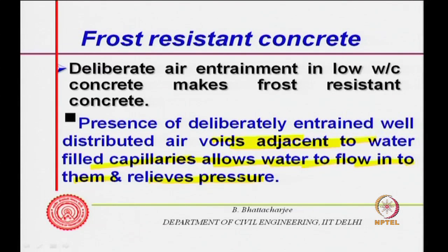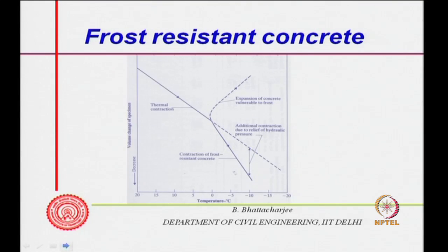So, therefore, it can last. But the deliberate air entrained voids, once the water enters there, become part of the interconnected pore system. During the next thawing, the water will penetrate into it, but all the air voids will not be filled in one go. Some will get filled by water and come into the interconnected permeable pore space, but some will still remain for the next cycle, and the next, and so on. So, the number of cycles air entrained concrete can withstand is much higher than non air entrained concrete, and this can be seen from this diagram.